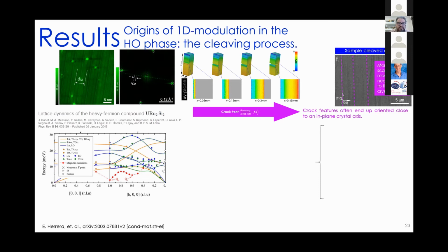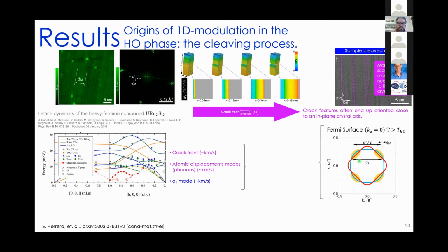We calculate that the dispersion relation for the Q1 mode is of the order of kilometers per second, the same order as for the crack front and also for the phonon modes. Therefore, we can link together the external action of the crack front, the atomic displacement, the phonons, and the electronic fluctuations at Q1. From the Fermi surface point of view, we can see this interaction as a combination between the hot spots in the hidden order state close to the Q1 vector and the atomic lattice. This combination is a consequence of the cleaving process, represented here by the pink arrows. When we cleave the crystal, we increase the interaction between these hot spots and the atomic lattice, and the result is a new modulation.